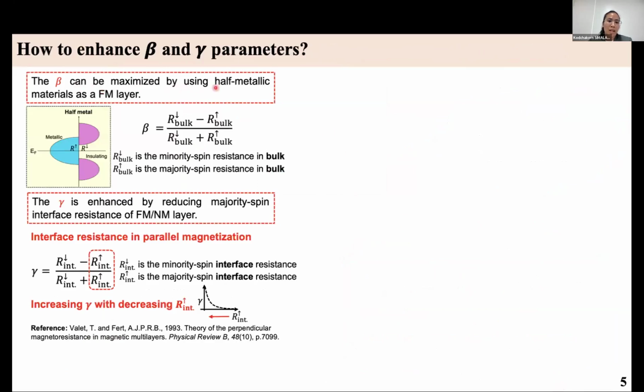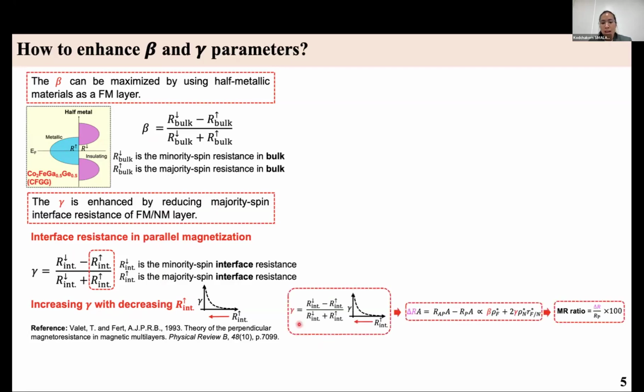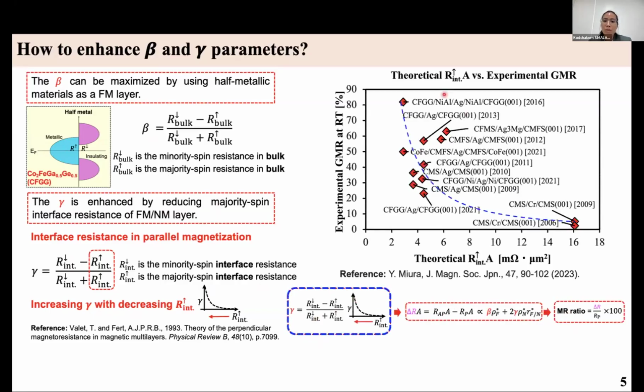Beta can be maximized by using half-metallic materials as the ferromagnetic layer, such as cobalt iron gallium germanium, or CFGG, because it provides ideally 100% spin polarization at the Fermi level. Gamma is enhanced by reducing the majority spin interface resistance in the parallel configuration, which can be described by this equation. Combining these two factors leads to an improved MR ratio, as shown by this relationship. Then to validate this theoretical concept, the correlation between theoretical interface resistance value and experimental GMR at room temperature was investigated in a previous study, as shown here. So this correlation shows that reducing the majority spin interface resistance increases the MR ratio in the experimental result.